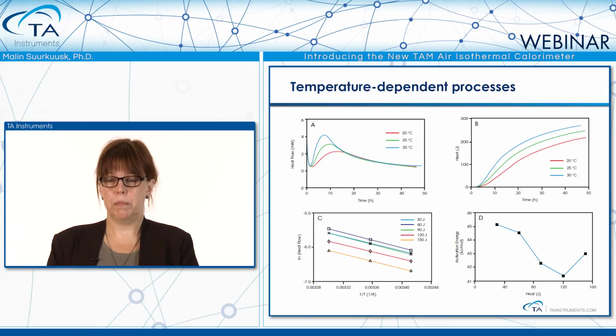Another example is the temperature-dependent processes. The cement process is very complex, and it is affected by temperature. In the upper left curve, A curve, you can see 3 cement samples measured at 3 different temperatures. And we can see the higher the temperature, the faster the reaction rate. If we integrate this curve and go to the upper right curve, we have the extent of the reaction, where we have the integrated heat flow. So we are plotting the heat versus the time here for the different temperatures.